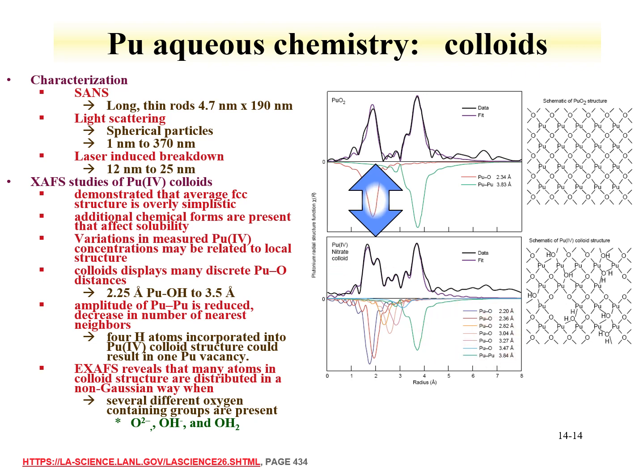What we do see that is similar is the plutonium-plutonium bond distance from both these data being around 3.83 angstroms for the plutonium dioxide and 3.84 angstroms for the plutonium colloid structure. So this data and these computations do give credence to the plutonium colloids being an extended oxide type species. And again, this is driven by the strong plutonium 4 hydrolysis properties.